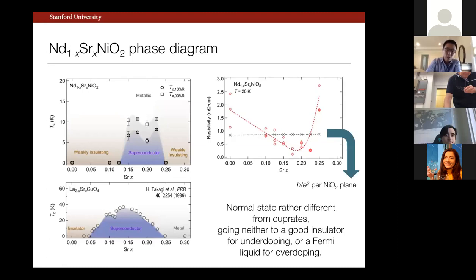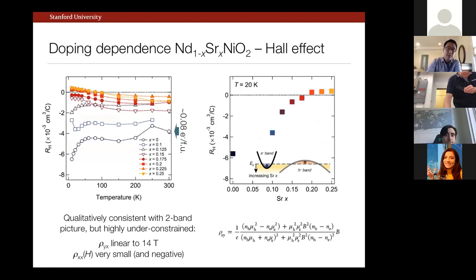So one of the things that we, of course, wanted to ask ourselves is, from a chemical formula point of view, we think we're doing hole doping, but what does the Hall coefficient tell us? And this is the doping dependence of the normal state Hall coefficient. There's quite a bit of data here, but again, there are some simple things that we can deduce. So here's the undoped neodymium nickelate. The Hall coefficient is negative, and if I naively attribute this to a single band free electron-like picture, the carrier density we would get is something like 8%, or 0.08 electrons per formula unit.